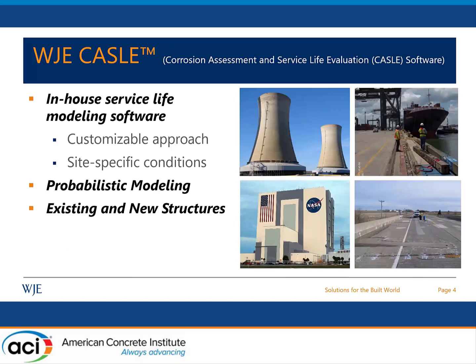So after that, we feed all of this data into our service life modeling software. We use WJE CASLE. It's a diffusion-based model that also considers the convection zone near the surface, where chloride transport is not necessarily governed by diffusion. Being developed in-house, WJE CASLE offers us full control over the evaluation process to facilitate a customizable approach to the circumstances and the exposure conditions unique to each structure.